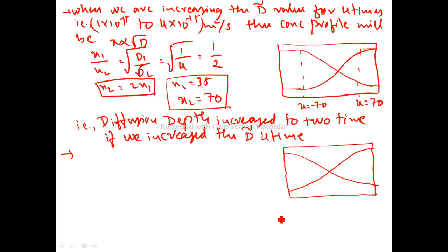See, towards this terminal we have the diffusion coefficient value of 4 into 10 power of minus 15, but here we have a lesser diffusion coefficient, that is 1 into 10 power of minus 15, meter square per second. Then the slope of the profile changes. It has a shallow slope here and a steep slope there, because of its D value.